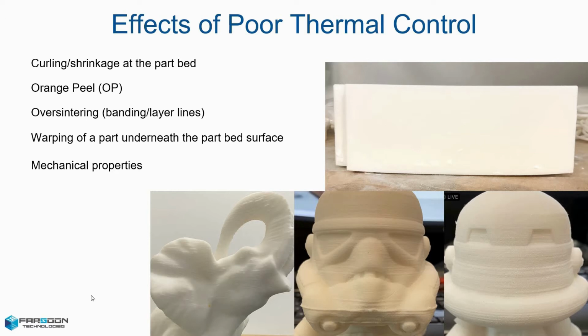Next, we have orange peel, sometimes referred to as OP. This is seen vertically in the z-axis on a part surface. This indicates that the part or parts were built in a cold spot or that the part build temperature itself was insufficient. If a certain area of the part build is identified, then raising the corresponding heater ratio is recommended. If all parts in the build have orange peel, raising the part bed temperature is advised.